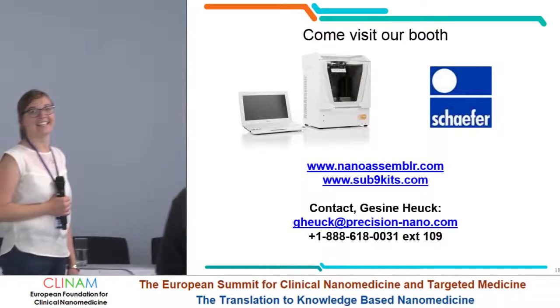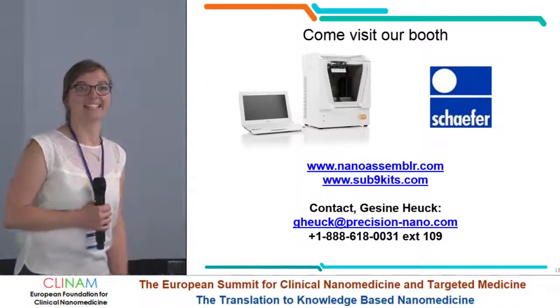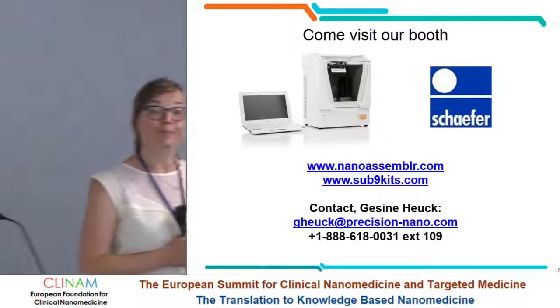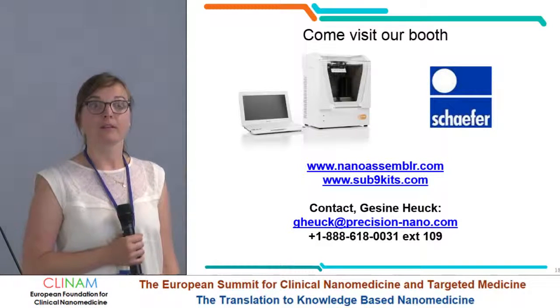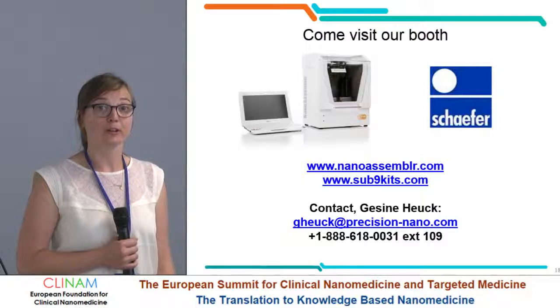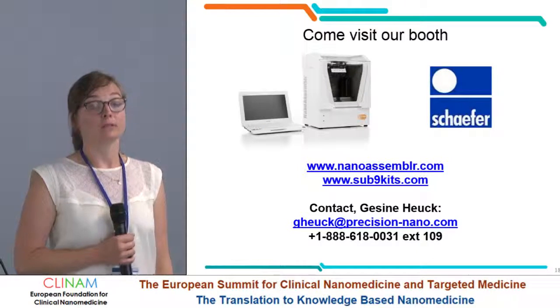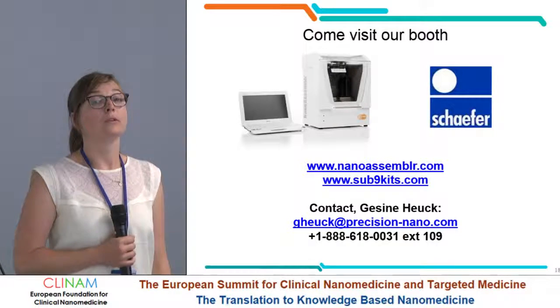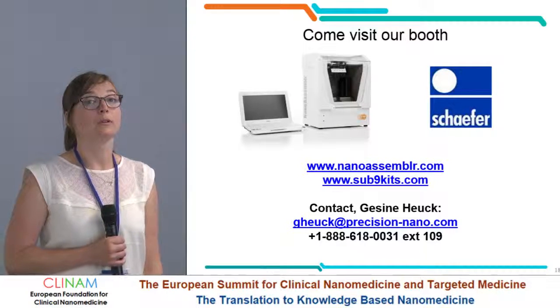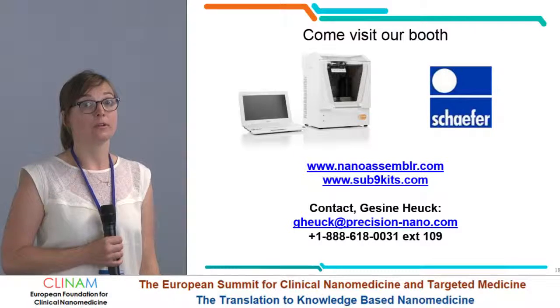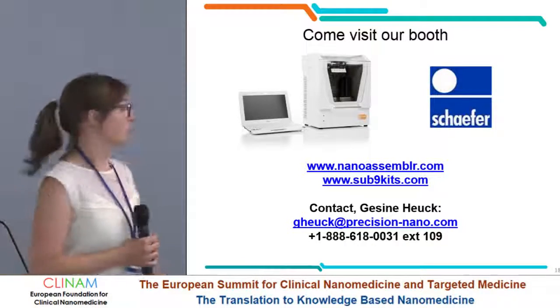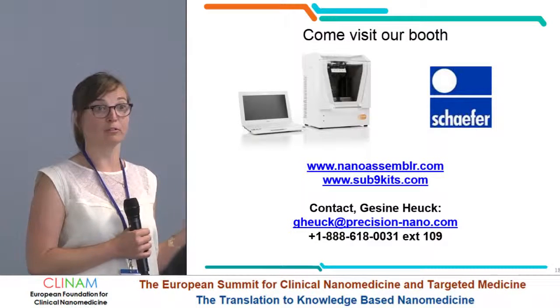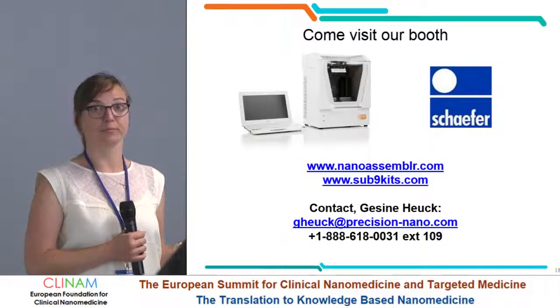I have a technical question: what is the encapsulation efficiency you reach with this apparatus, and can you check it online during synthesis? The encapsulation efficiency with these nanoparticles is over 96% — we're pretty much encapsulating everything. That is because we have a complexation reaction where the negatively charged oligonucleotide interacts with the ionizable lipid nanoparticles.